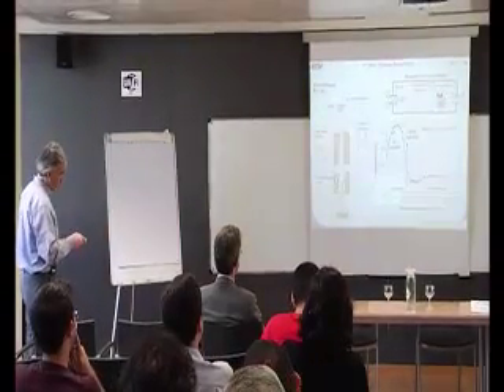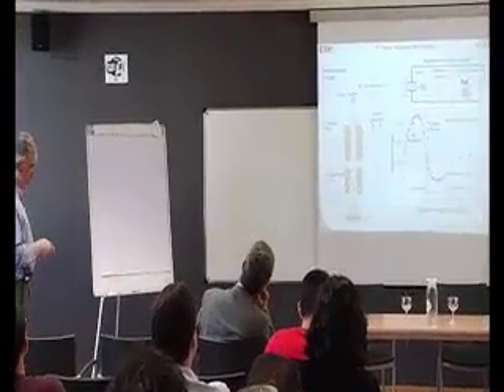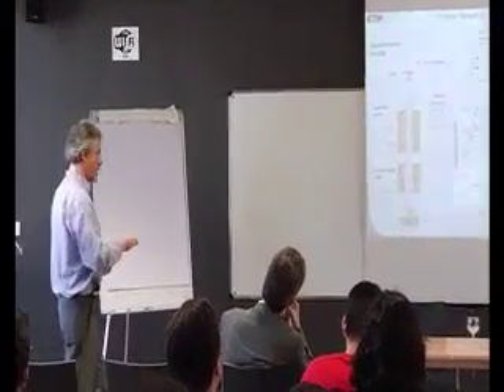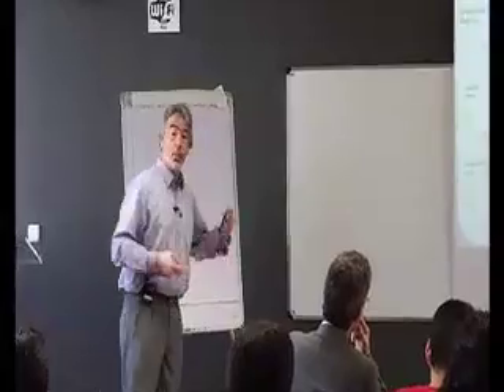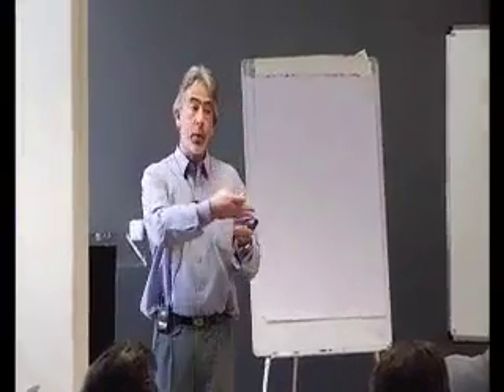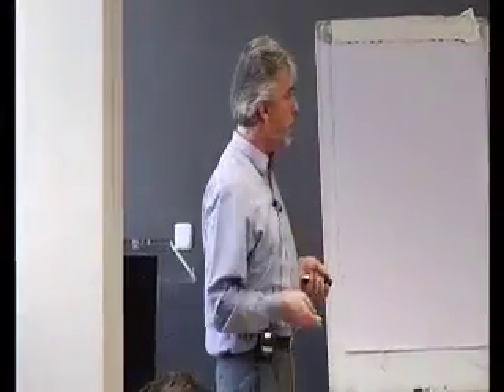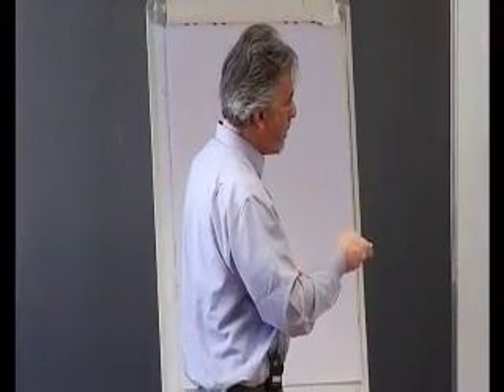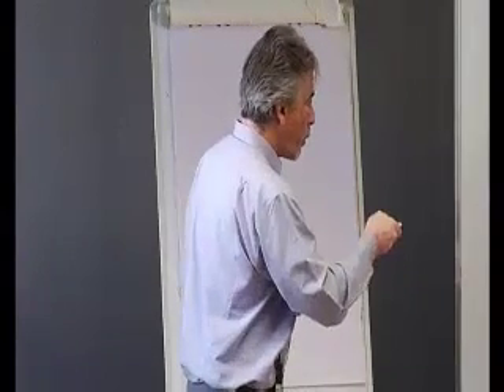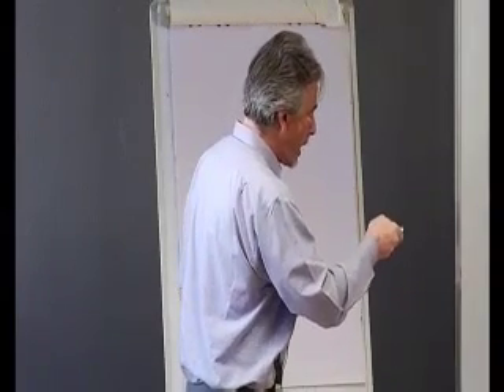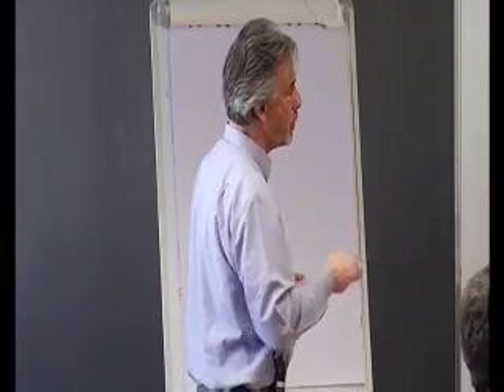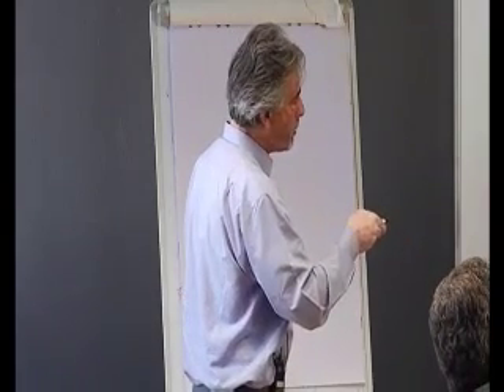In the lower one, this is where we place the zinc sample, which is evaporated. We have a balance to monitor the weight loss and calculate the mass flow rate of zinc vapor. And then at this location, we mix with steam, we quench to form the nanoparticles that react as the nanoparticles and steam flow together through this reaction zone. Here downstream we collect the particles and we analyze the gases.